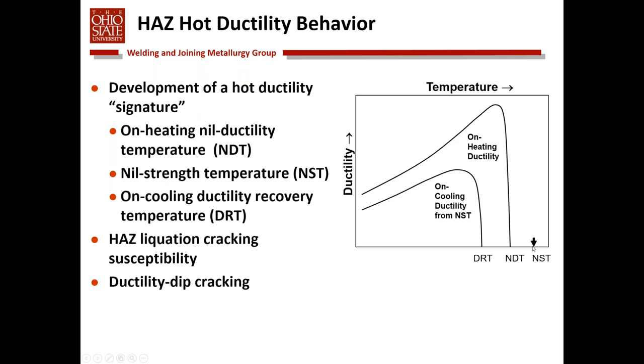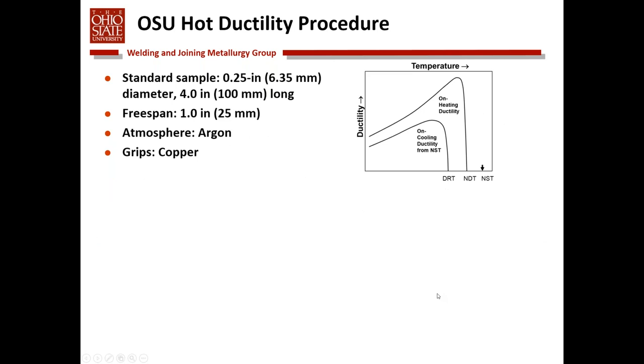The nil strength temperature, which is the temperature at which the material has virtually no strength. So this is a temperature that's at or slightly above the solidus temperature of the material. And the ductility recovery temperature, which means if you heat the material to the nil strength temperature and then cool down, at what temperature does it start to recover its ductility? The differential between the NST and the DRT is very predictive of heat affected zone liquation cracking. This test can also potentially be used to look at ductility dip cracking, which would be manifested by a drop in ductility at elevated temperature.